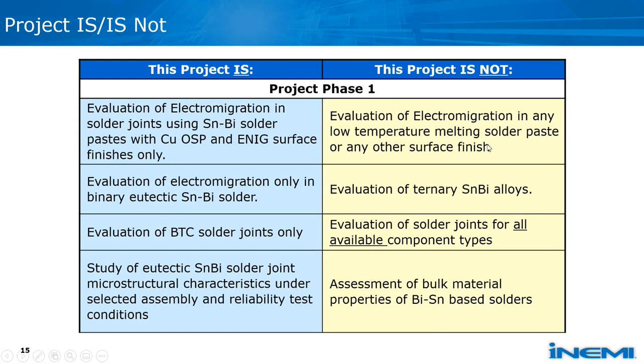Next slide. This slide defines what the project covers and what it does not cover. Solder pastes in the tin bismuth system will be used to form solder joints for electromigration evaluation. We're going to use solder paste with no clean flux in them. So surface finishes looked at will be copper OSP and electroless nickel immersion gold, also known as ENIG, as I said before. The eutectic composition of the solder in the tin bismuth will be evaluated. Off-eutectic tin bismuth solders, such as having less than 57% bismuth, or ternary alloys such as tin bismuth silver, or even alloys with dopant additions to improve their properties, will not be evaluated in this phase 1.